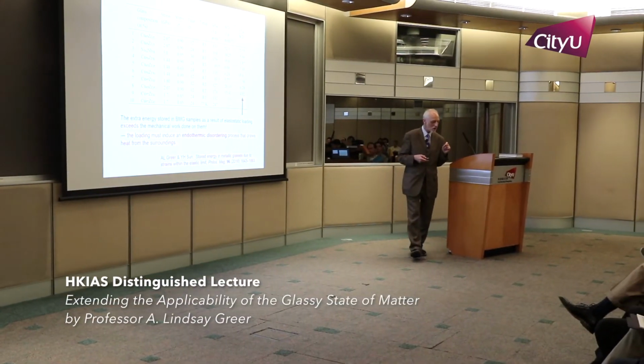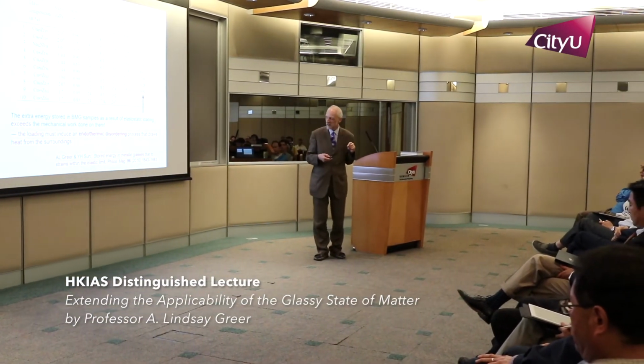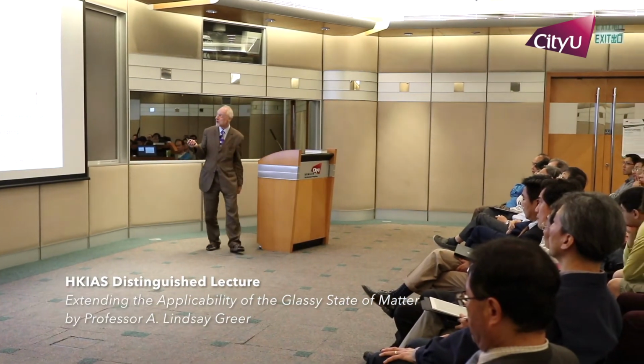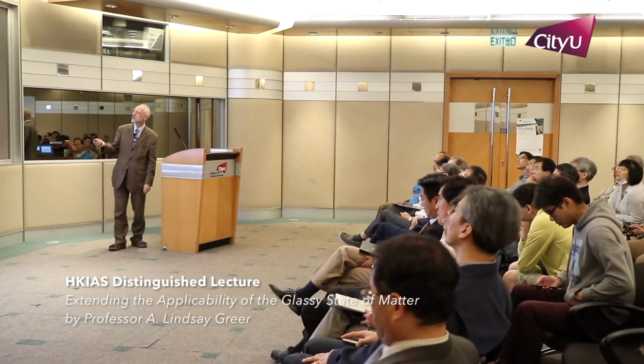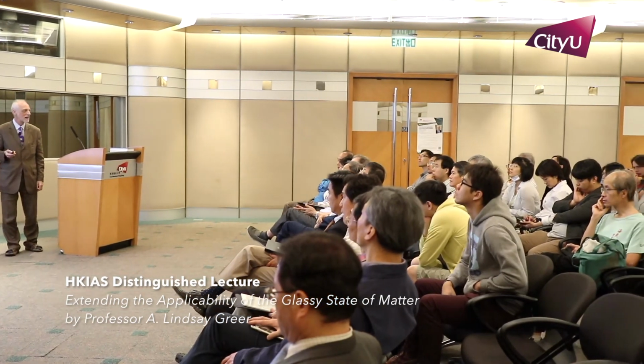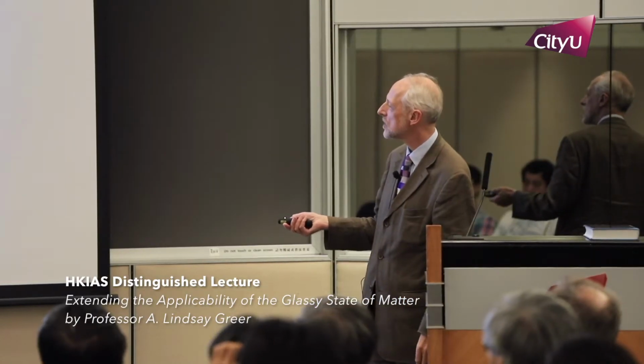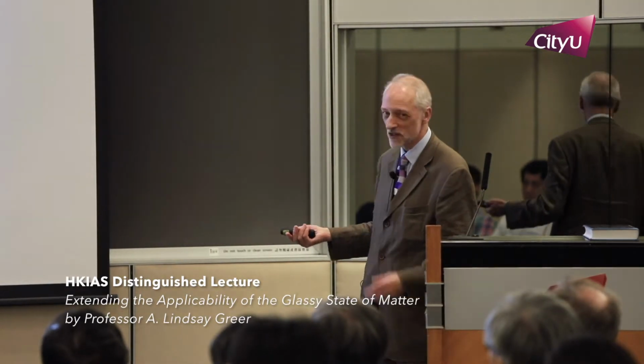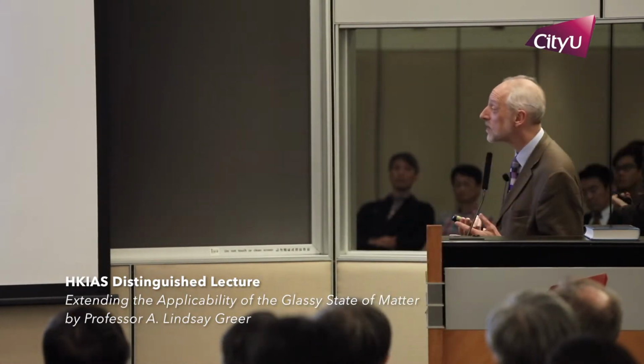And the stored energy now is not a fraction of the work done, it is several times the work done. So in fact, you can get stored energy that's almost 20 times the mechanical work done on the system, which must say that the energy comes from something entirely different. The work done, of course, is exceedingly easy to calculate from the distance moved by the load. So it can only be that the loading is inducing an endothermic disordering that's drawing in heat from the ambient surrounding the sample. So again, an interesting process that needs further study.